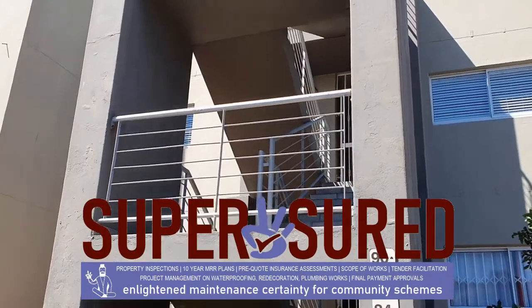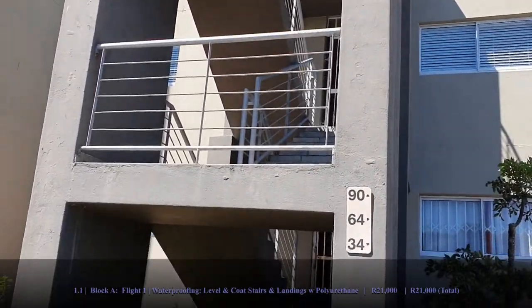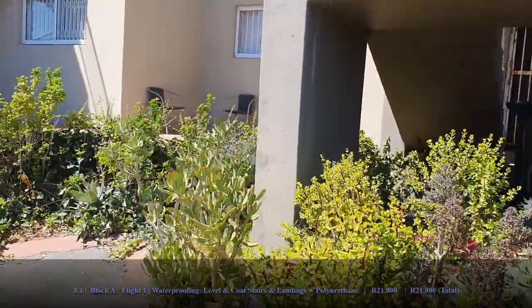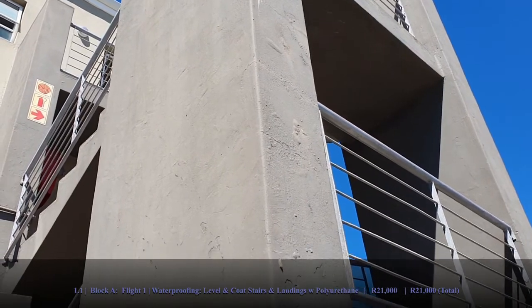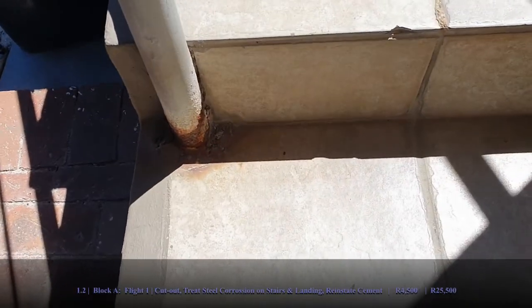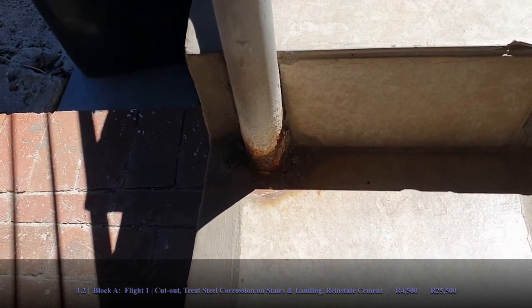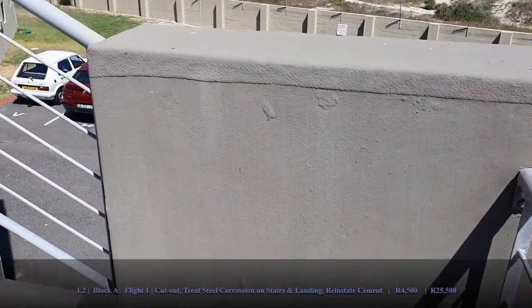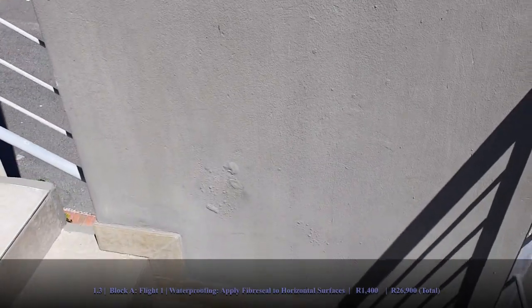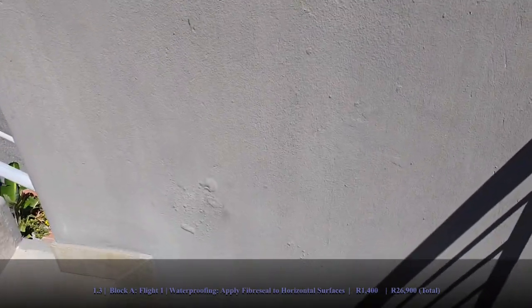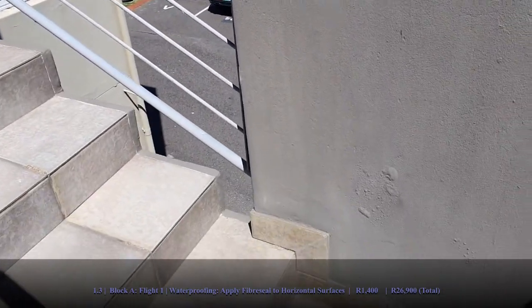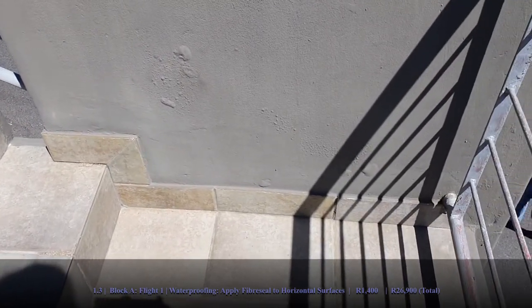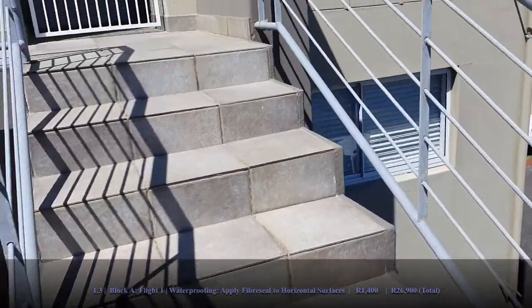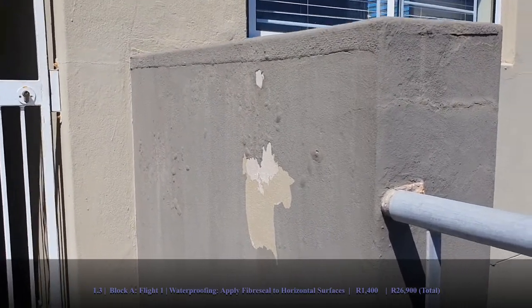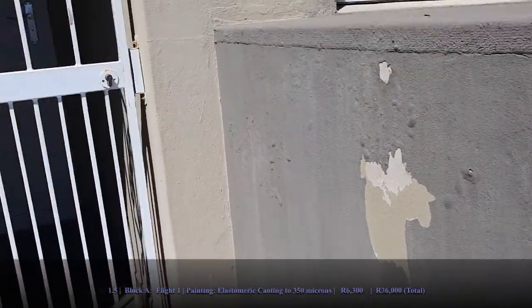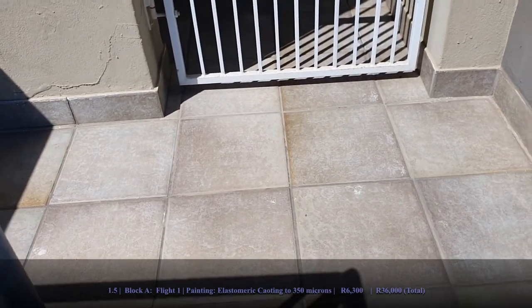Obviously these steps need to be done, and you can actually see that this particular stair block has taken quite a lot of problems with water ingress. There's quite a lot of bubbles and peeling here because of the water coming in. There are also issues with the railings and the uprights, especially around the feet corrosion. The top of the parapet walls has a membrane on it which is helping with some of the waterproofing, but obviously you can still see that there's water getting into these walls, and most of it is probably siphoning up from getting into the substrate because there isn't proper waterproofing under the tiles. So we would also recommend redoing the entire walls, repainting them on the stairwells after addressing the waterproofing of the tiles.